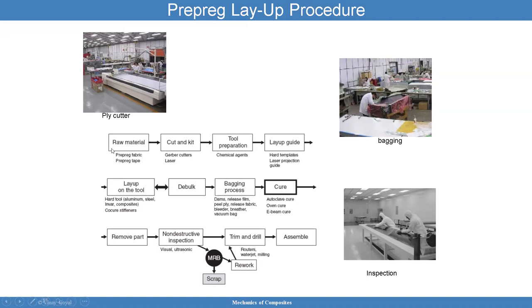Then I go through a debulk process and I have the bagging process. The bagging process means I'm going to protect the layup in such a manner that I can actually pull the vacuum. And also so things don't get stuck to each other. So you need the release film so you can release the composite. You have the peel ply, the release fabric, the bleeder, the breather, and the vacuum bag. Then you go ahead and cure. You can do it in an autoclave or an oven.